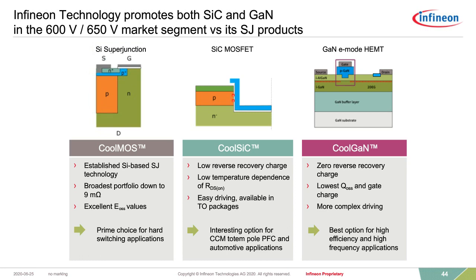Moving forward into silicon carbide, especially in the 600-650-volt domain, the key advantage of silicon carbide is its very low dependency of the on-state resistance as a function of temperature. A very interesting option for the totem pole, where we see clear acceptance in the market in, for example, data centers. Gallium nitride, the technology as a lateral device with very small capacitances and extremely small gate charge, is the perfect device for high frequency operation in data centers, for example, moving the LLC stage into 300, 400 kilohertz, potentially up to 1 megahertz. So having access to all of these three technologies, we can guide our customers to whatever is best suited for the specific application the customer is dealing with.